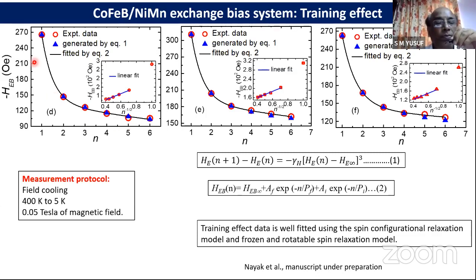There is a sudden drop in exchange bias field from n equal to 1 to n equal to 2. Therefore, we could not fit the data using the thermal relaxation model, and so we used these two equations, this frozen and rotatable spin relaxation model and this spin configuration relaxation model, to fit the data, and the data is well fitted with these two models.